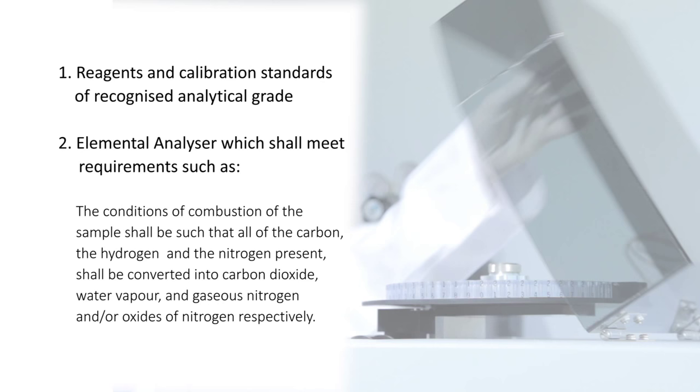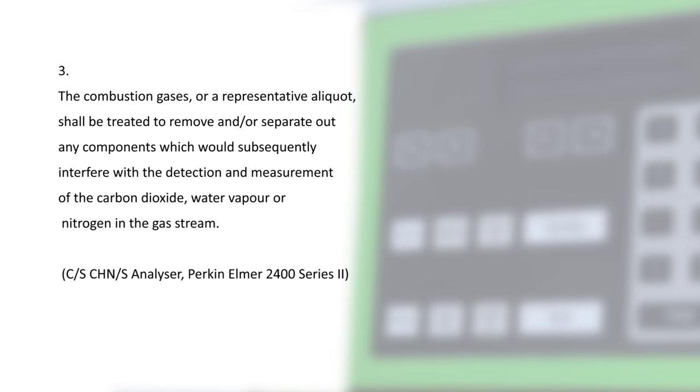The combustion gases, or a representative aliquot, shall be treated to remove and/or separate out any components which would subsequently interfere with the detection and measurement of carbon dioxide, water vapor, or nitrogen in the gas stream.